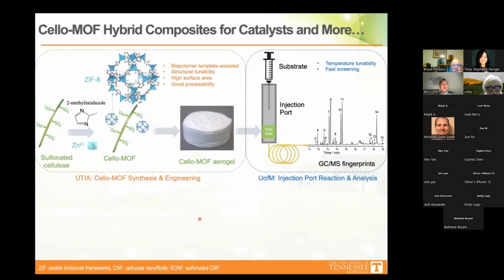And the second story is also about nanocellulose-based functional materials. And Nicholas knows some, because I'm collaborating with Nicholas on this part. Okay, so as I mentioned, the nanocellulose usually bears a negative charge on the surface. So this is a sulfonated nanocellulose. What we are doing right here is to leverage the negative charge on the surface, and to anchor a metal ion first, based on the electrostatic affinity. Then we will add a chemical, and this chemical will form a coordinate structure that looks like a cage.